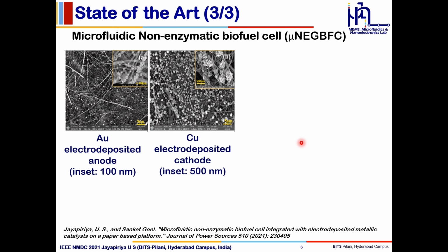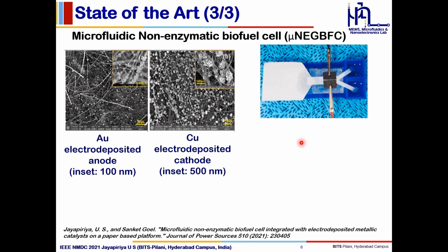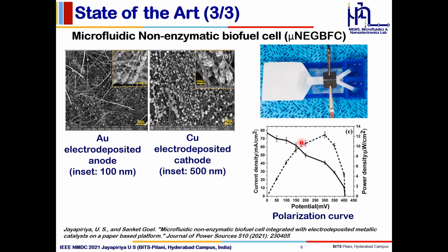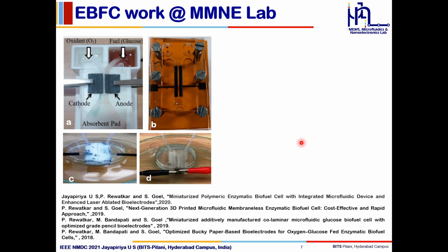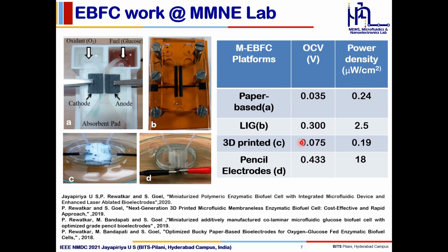The next work done in our group is a microfluidic non-enzymatic biofuel cell, wherein we used a gold electrodeposited anode and a copper electrodeposited cathode on CNT Bucky paper, which was integrated on a paper-based Y-shaped microfluidic channel to harvest power. This biofuel cell was capable of producing a power of 12 microwatts per centimeter square, which is quite commendable for a paper-based platform. These are some of the other works where enzymatic biofuel cells have been developed in our group using different electrode materials like Bucky paper, pencil graphite, laser induced graphene. These electrodes were capable of producing a good amount of power density also.